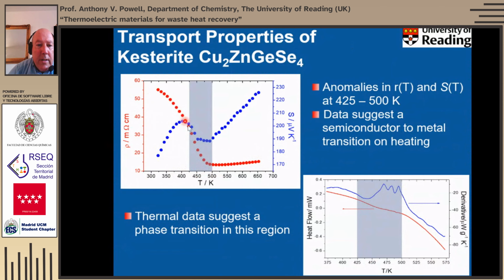So here's the resistivity, clearly semiconducting behavior, and then it turns around and starts to increase, and the Seebeck shows anomalies as well. And also we find that DSC data show quite significant changes in slope in that region, which maybe show up more clearly if we take the derivative of the heat flow. But nonetheless, we have something going on in that region where we have quite marked changes in electrical properties.